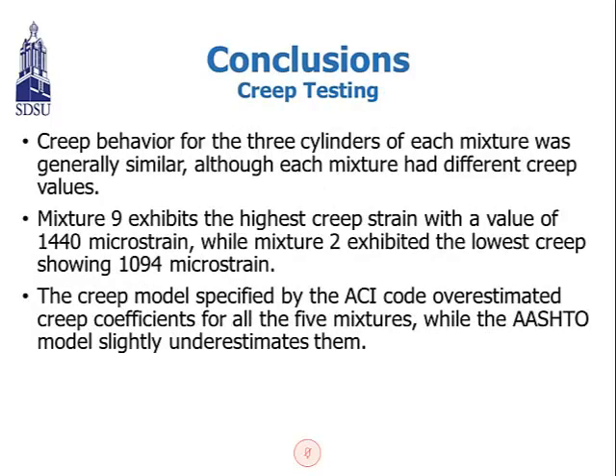And the conclusion from the creep testing: creep behavior for all three cylinders for each mixture was generally similar, although one mixture had a different creep value. Mixture 9 exhibited the highest creep strain, a value of 1440 microstrain, while mixture 2 exhibited the lowest creep, showing 1094 microstrain. And the creep model specified in the ACI code overestimates, as I showed in the figure, the creep coefficient for the mixtures, while AASHTO slightly underestimates them.